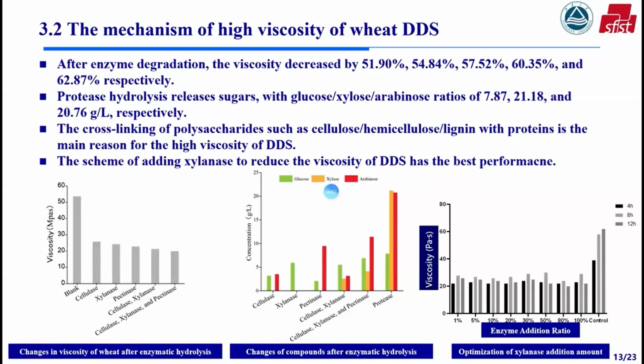After being treated with different enzymes, macromolecular compounds are hydrolyzed into small molecular compounds, breaking the intercross linking state between macromolecules. As a result, the viscosity decreased by more than 50% in all cases, with the maximum reductions reaching 62%. Among these enzymes, xylanase exhibited the optimal performance in both treatment effects and economic cost. Therefore, it is recommended to use xylanase treatment to reduce the viscosity of DDS, thereby facilitating downstream processing.